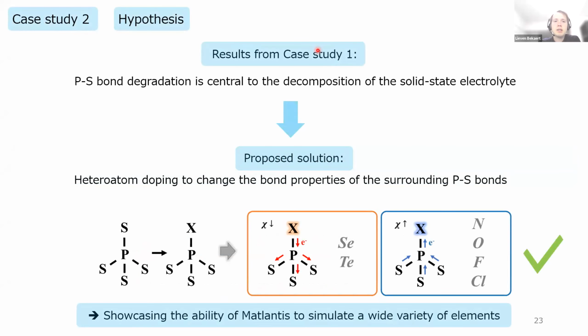As I explained to you a few slides ago, we found that this PS bond degradation is central to the decomposition of the solid state electrolyte. So how could you then potentially target a lower reactivity towards sodium metal? Well, one of the ideas that we had was, can you change the chemical properties of these PS bonds? And could you do that, for example, by replacing or doping one of these PS bonds by a PX bond? So you introduce a heteroatom to bond with phosphorus.